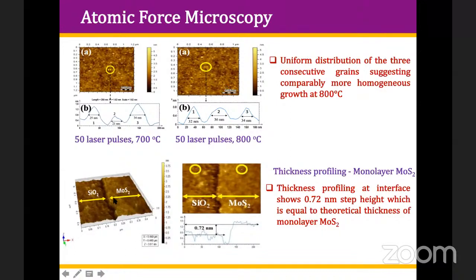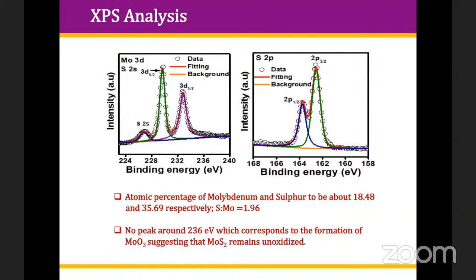And you can see the thickness here where the bottom layer was SiO2. Over the SiO2, MoS2 has been grown, and we got a thickness of 0.72 nanometer. And we have just shown you in the beginning, in literature, the thickness of a monolayer is around 0.65 or 0.7 nanometer. So that means we clearly obtained the monolayer, and the thickness is obtained from the atomic force microscopy, which shows a monolayer growth with uniform distribution of grains by using pulsed laser deposition.